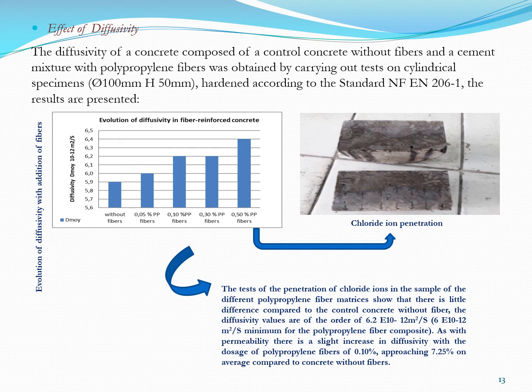For the effect of polypropylene fibers on the diffusivity, the chloride ion penetration tests in the samples of the different polypropylene fiber matrices show that there is little difference compared to the control concrete without fiber. As with the permeability, there is a slight increase in diffusivity with the dosage of 0.10% polypropylene fibers, approaching 7.25% on average compared to non-fibrous concretes.